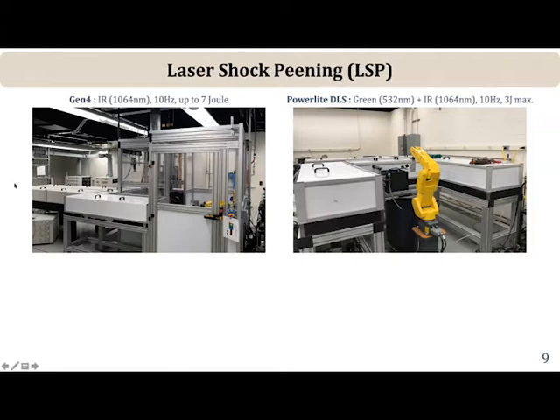Besides that, we also had a Powerlite DLS system, a 3-joule system in the infrared mode, and also the green. So this also had a green laser, so you can actually do some underwater peening. We've done those kinds of studies as well, and actually that has a very remarkable effect, especially when you do the laser peening without using any ablative tape. So this shows a small cell that we had built along with a robot, so you could essentially do peening underwater as well.